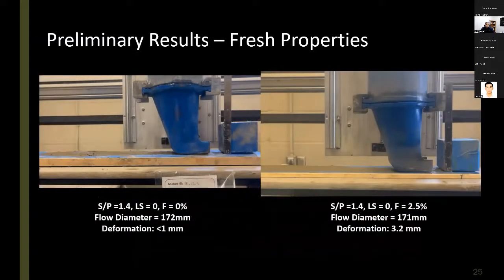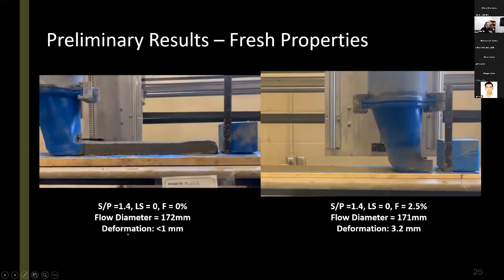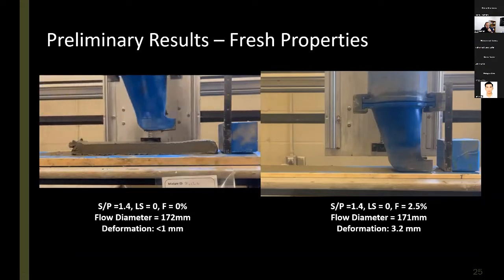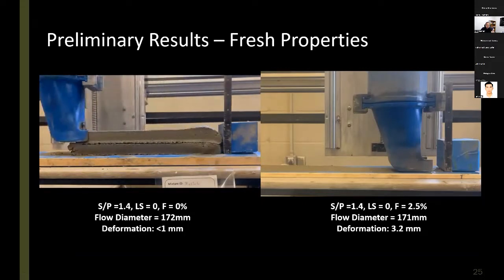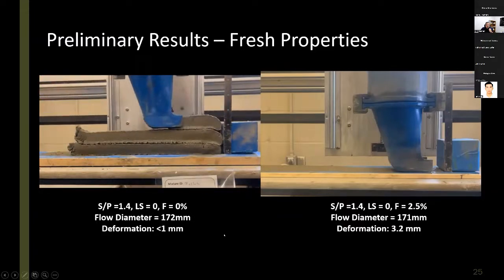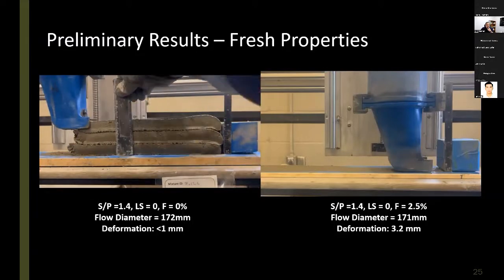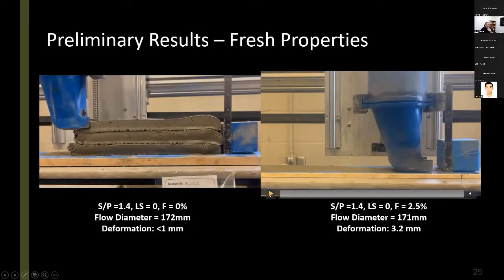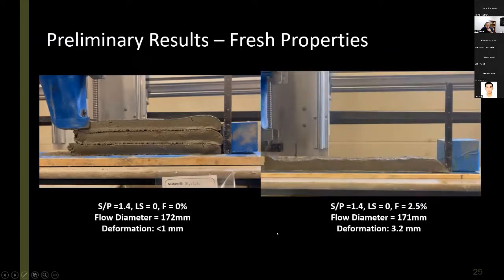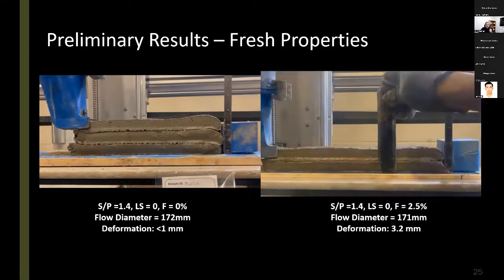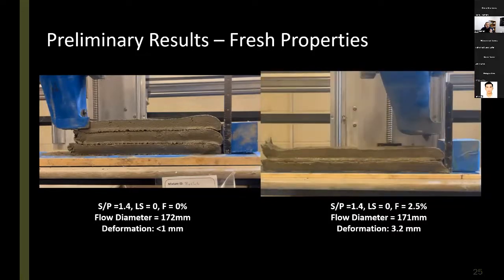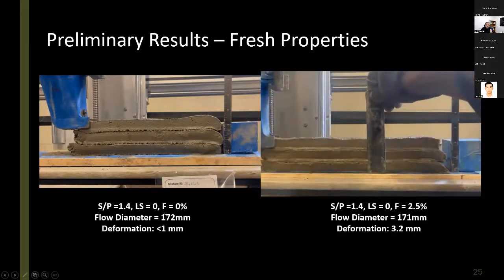I'm not going to present all the results because of the limited time we have, but just to give you an idea of the data that we have collected so far. These are some experiments in terms of shape stability. This one is a mixture with a better and higher shape stability, so lower deformations, as you can see, lower than 1 millimeter, which is acceptable and very encouraging. And then a mixture with higher dosages of steel fiber that, as you can see, some deformations here we can see and we can measure, which is more than the previous mixture.